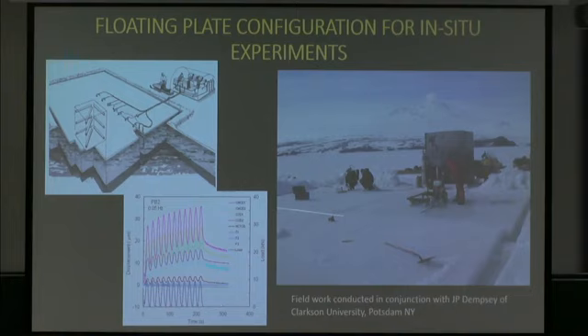My part of this, the model we'll be talking about, does the characterization of the whole sheet. So once you realize you can quantify that, then when you analyze a fracture experiment, you can pull out the constitutive response of the whole ice mass and be left with just the response around the crack tip and the damage zone. This just gives you a little idea.